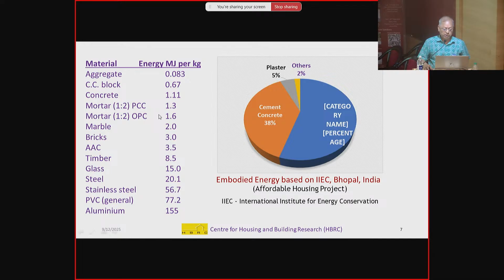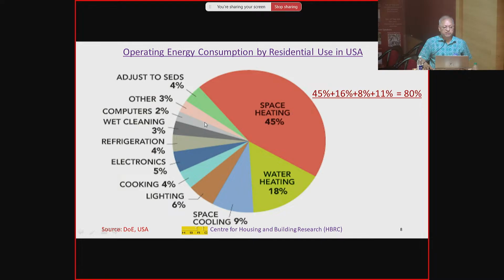So if it is 1:2, the energy consumption is 1.3 if we use composite cement. But if we use ordinary Portland cement, then the energy consumption is more, 1.3 to 1.6, because in composite cement maybe 30-35% is fly ash or blast furnace slag, which is not contributing as much carbon as clinker contributes. So considering these things, we have to select our building material and technology.